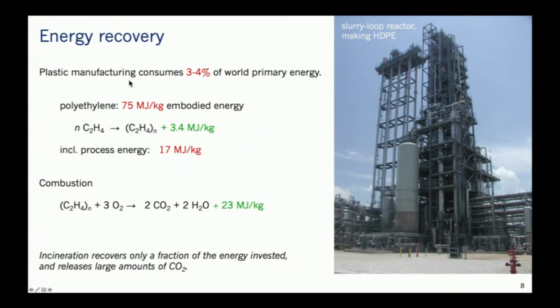And so the counter argument here is that making these plastics is incredibly energy intensive. We're currently using about 3 to 4% of primary energy just to make these materials. And the example for polyethylene here shows this enormous amount of embodied energy, which is partly the feedstock energy and partly the process energy. Even though the process of polymerizing ethylene is actually exothermic, you have to do that in these enormous reactors and you have to remove heat. And at the end, you have to remove solvent. And so you actually spend a lot of energy to make these polymers. When you combust them, under the most ideal circumstances, you get back just a fraction of the energy that you invested. So it's not an inconsiderable amount, but it's certainly much better to think about ways to get more value out of the energy that you've already invested in these polymers.